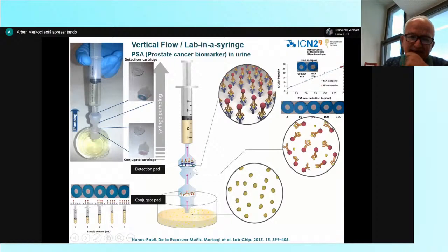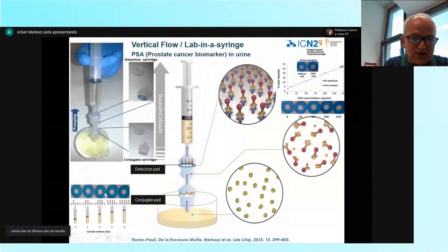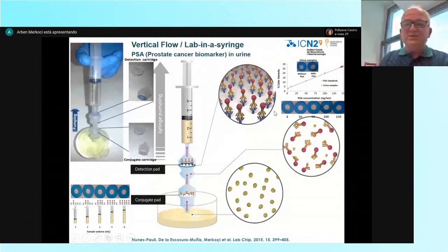So the nice thing here is that the sample can be taken, for example, 5 milliliters of urine in the case of a prostate cancer biomarker. And the nice thing is that the system here is used to pre-concentrate the biomarker. So at the same time, we do pre-concentration and we get the results immediately. You can see here the change of the color that corresponds to different concentrations. So you can see the increase of the color based on the increase of concentration of PSA. So this is really very interesting, and can also be used for preconcentration of, for example, virus in the case of big volumes of samples. So this is a very nice application of interest for real applications in different areas where you need to do a preconcentration of the sample.